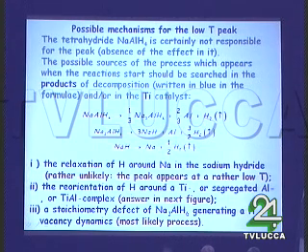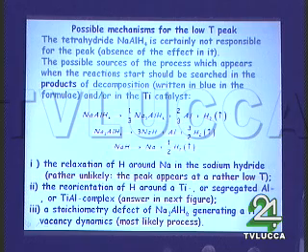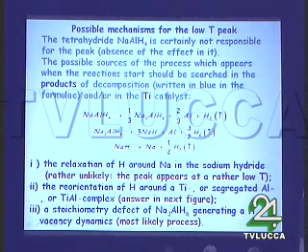The reorientation of H around titanium, or segregated aluminum, or a titanium-aluminum complex, so the answer will be in the next figure. The most likely process is a stoichiometry defect of the hexahydride generating a hydrogen vacancy dynamics.